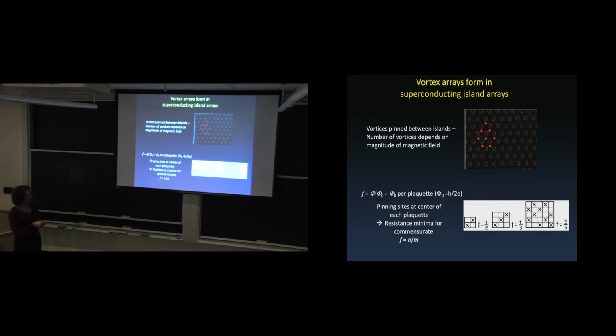If it's 2/5, it means we have a flux quanta in 2 out of 5 plaquettes, and they arrange themselves into a lattice, right? But this is interesting because vortices are interacting. When they arrange themselves into a lattice, they pin. So if I'm measuring resistance, what I expect is that when I have a commensurate lattice, which is some rational number n over m, I have lower resistance. When it's non-commensurate, I have higher resistance.